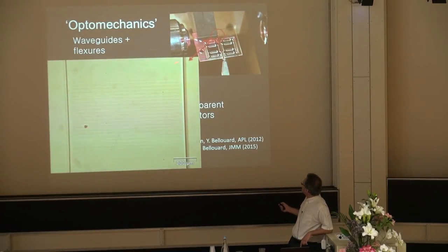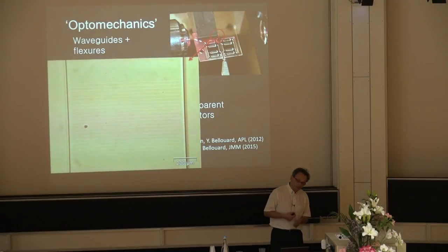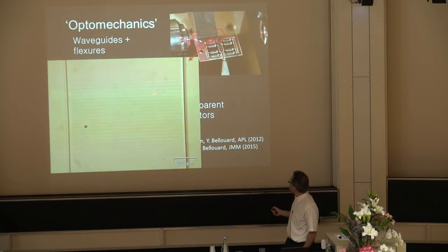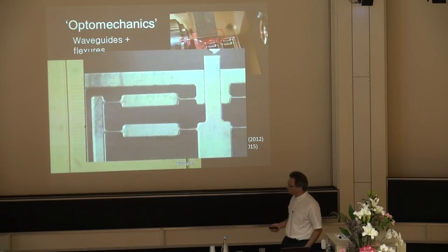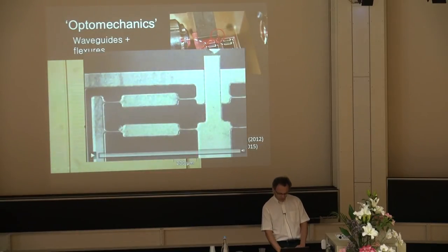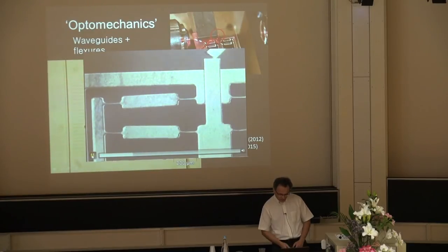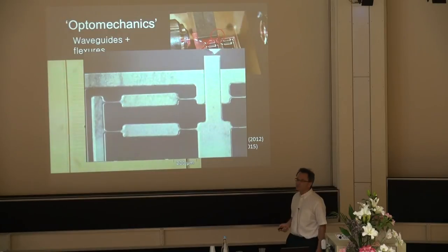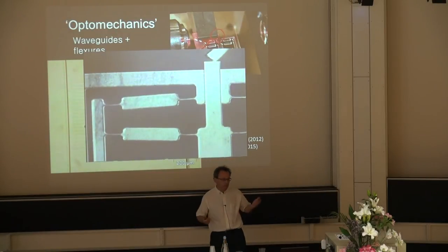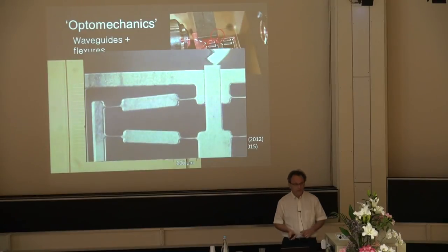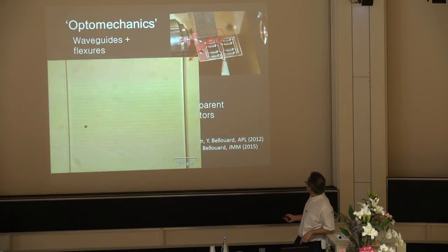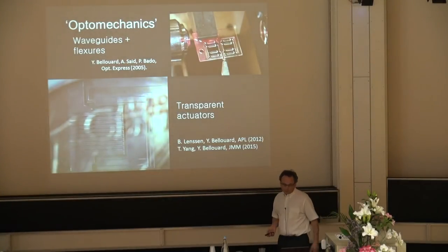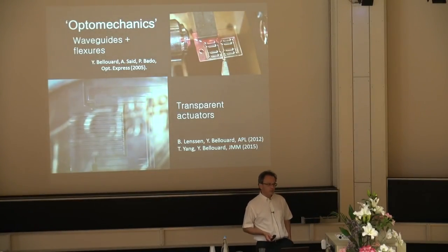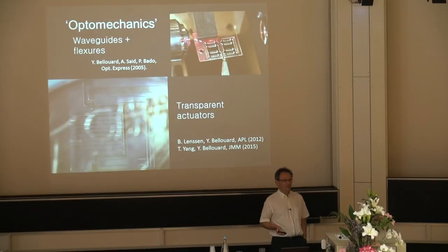So if I combine these waveguides with some mechanical guidance, now I can make a fully integrated device where I have a guidance in which I have some waveguide that gives me information on the position of the device. Let me show you this guidance. So this is glass again. And then you see when I press on it, the gap here in between is 15 microns. So that's about 1/4 of a hair, typically. So it's obviously a good guidance. Well, glass is transparent, so why not? You can make a transparent actuator. To be honest, we don't know what to do with it yet, but it's fun.